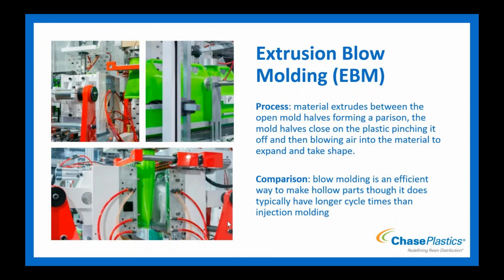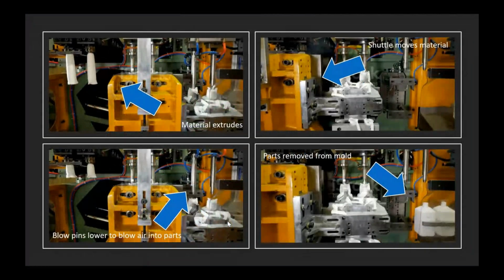Extrusion blow molding starts with extruding the material out, the mold clamps on it, then we blow air into it to form your part. We have a run through of that process here. If you look over here, you have material that's being extruded out. Then this shuttle is going to come over and pick it up and move it back over here to where your pins are. These are your blow pins. They'll come down, blow air into it, and then it creates these little bottles right here. That would be your process through blow molding. There are more variables, but in a simple version, material comes out, we clamp the mold around it, blow air into it, and parts move on.